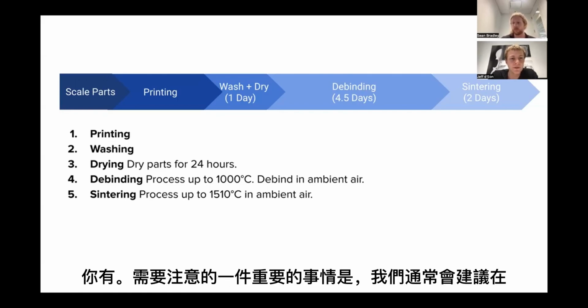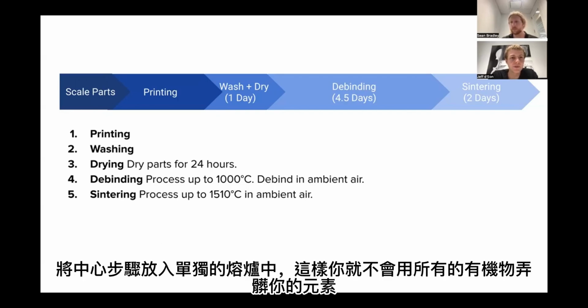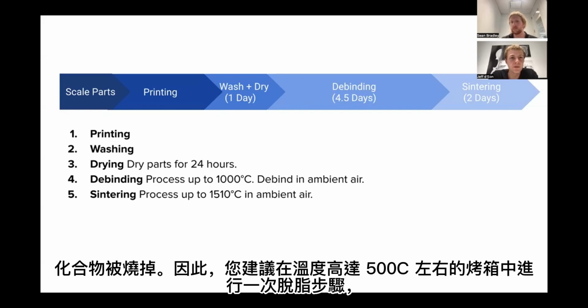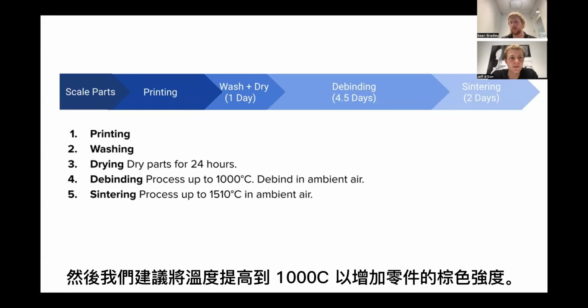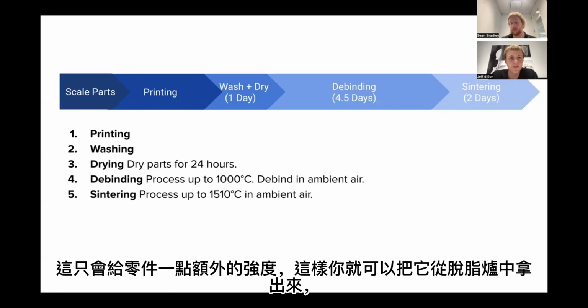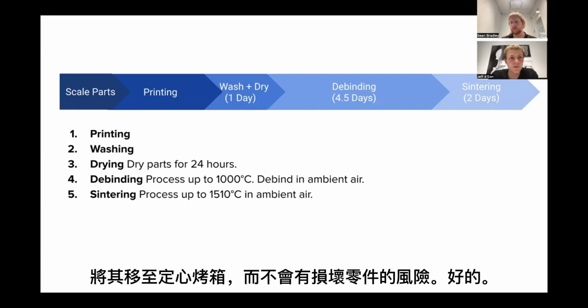One important thing to note is we do typically recommend doing the debinding step and the sintering step in two separate furnaces so that you don't gunk up your elements with all the organic compound being burned off. So we recommend doing one debinding step in an oven up to about 500 C, and then we recommend bringing that temperature up to 1000 C to increase the brown strength of your part. That'll just give the part a bit of extra strength so that you can take it out of your debinding oven, move it to your sintering oven without risk of breaking your parts. Okay.